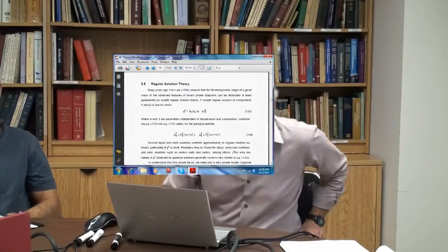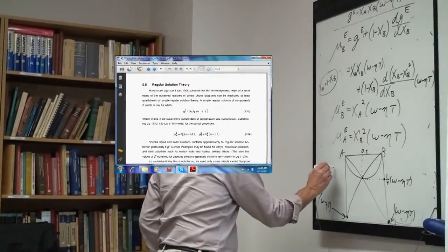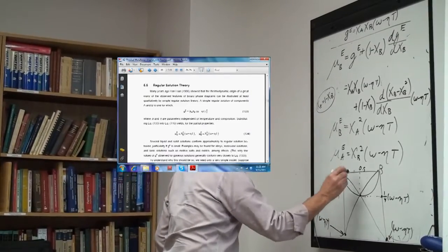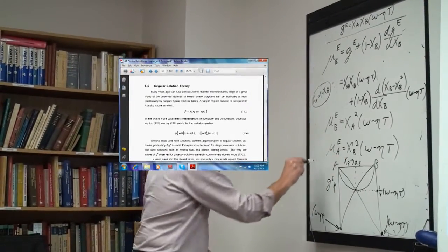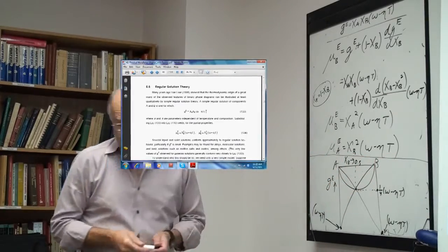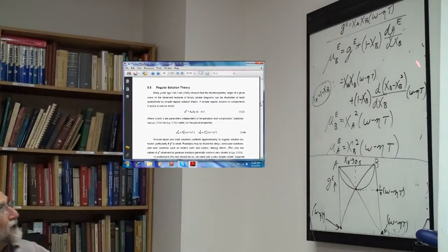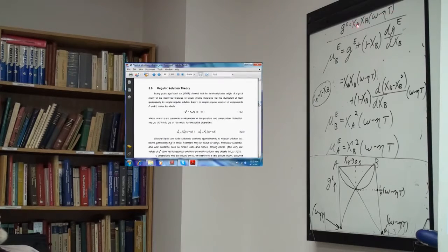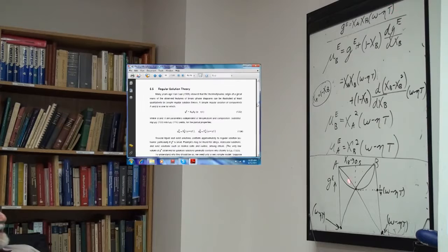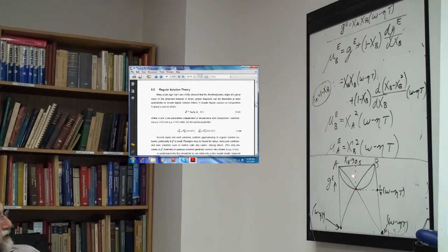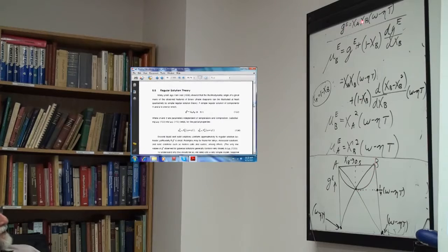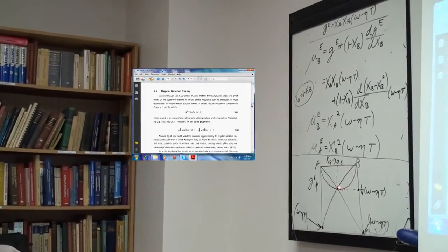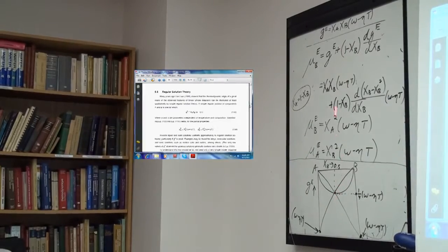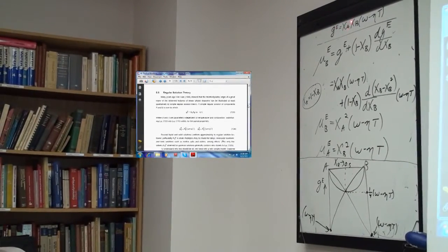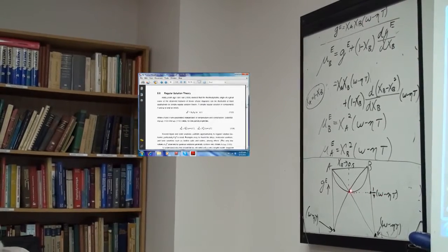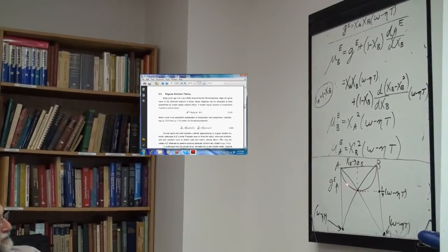This is a plot of G^XS versus composition, mole fraction of B. Up here we have the excess Gibbs energy. This is your regular solution, X_A X_B times omega minus eta T. If you plot this up, it is equal to 0 at both ends, of course, and goes through a maximum at 50%. At the maximum, G^XS is 1/2 times 1/2 times omega minus eta T, and it peaks out at 50%. That is a parabola.